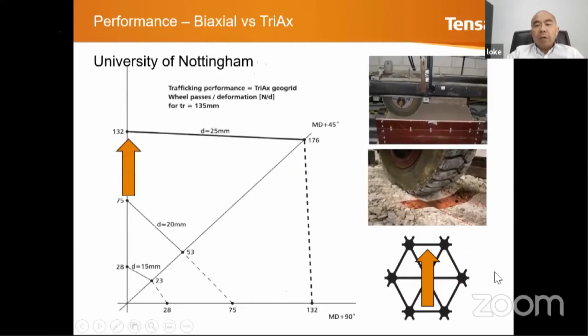Let's try it with a multi-directional or hexagonal geogrid. I do the same test. If I run 28 passes, I get 15 millimeters. At 75 passes, I get 20 millimeters. At 132, I get 25 millimeters if I run in this direction. What happens if I run it in the diagonal direction? You can see that I still need a very high number of passes to achieve the same rut depth. Why is that? Because you have a rib running in that direction.